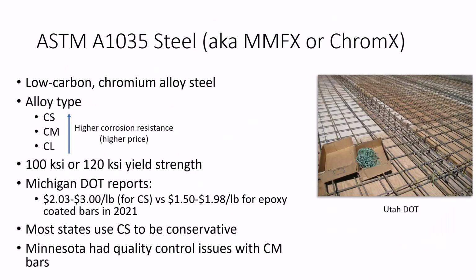And then we have the ASTM A1035 bars, which you may know them by their brand names, MMFX or ChromX. So these are chromium alloy bars, and we have three different types, CS, CM, and CL, with CS provides the highest corrosion resistance, and so of course that comes with the highest price. They come in either 100 KSI or 120 KSI yield strength. And most agencies that participated in the scan reported that they chose not to rely on that high strength, so that they just use it as a one-to-one replacement of our good old grade 60 steel, or you can just cap the yield strength in the design to be conservative.